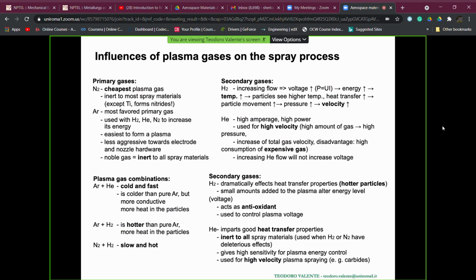for the plasma spray technology, which has been used, because if we are going to use, in this case, titanium, for example, with nitrogen, we can expect to have a subclass of plasma spray technology, which is called RPS techniques, that is reactive plasma spray. In this case, we want the reaction, and so we want the incorporation of nitrides inside the coatings. And thus, if this is desired by the designer, we can think to use, for example, in this case, nitrogen.